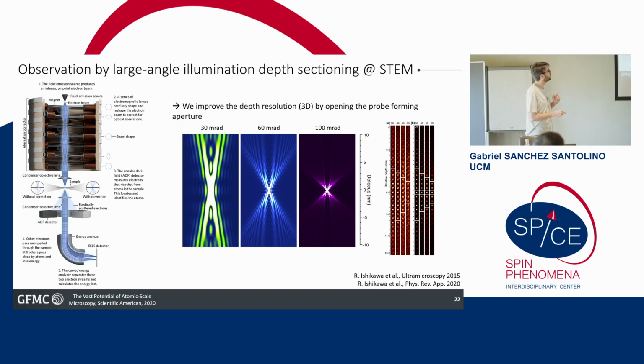So this is a more conventional microscope now with an aberration corrector that has a 30 milliradian convergence angle. So the probe is convergent, but not too much. But if we increase this angle with the new correctors, we are going to improve our resolution in the depth section, in the three-dimensional direction, basically. We are now at about 5 nanometer resolution, and we want to increase it, and we will get down to 1 unit cell resolution in the Z direction in a few years.